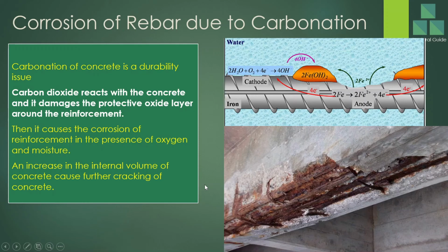With the damage of this oxide layer protection, it starts corrosion of the reinforcement. If there are smaller cracks, that air, that is oxygen and moisture, can penetrate to the reinforcement, and the corrosion will start. This will increase the area around the reinforcement. With the corrosion of the reinforcement, internal volume increases. This increase in the volume causes the cracking of the concrete. This is the cause of the spalling of concrete also. With the internal volume increase, the concrete will crack further, and your reinforcement gets more oxygen and moisture. With that, this corrosion will speed up and the concrete will further crack and spalling will occur.